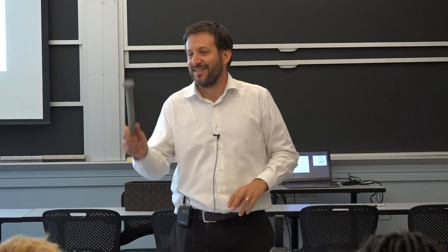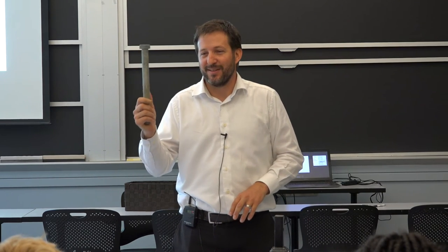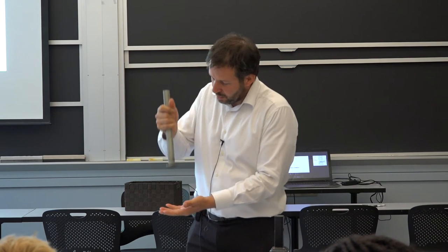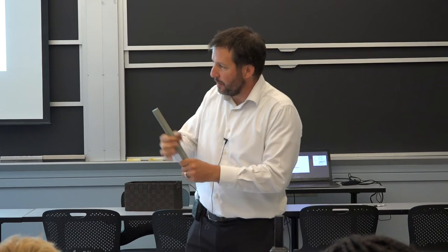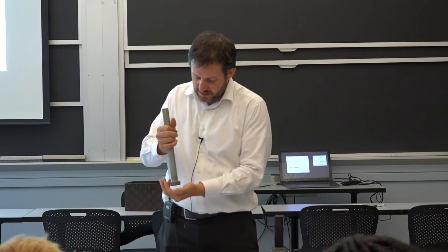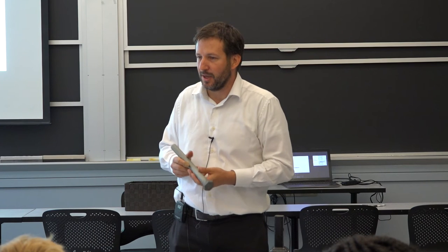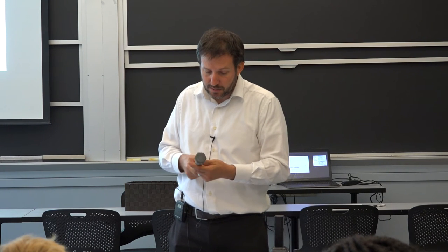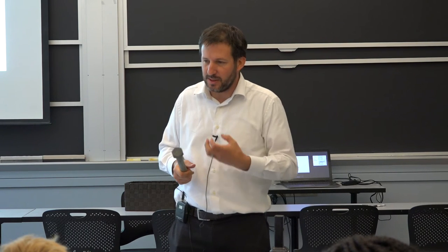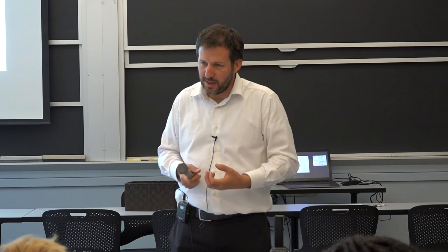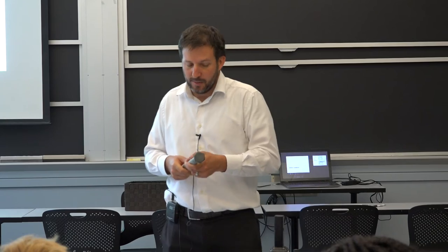What about this one? What do you guys think happened here? Hitting. Yeah, so it's cold pressed. It starts with a bar, and then you have a series of steps to mushroom the end of the bar to make that shape. It's actually very, very strong, so it's not going to break here because you forge the material, you deform it, and you actually make it better than it was to begin with. But you do need to do it by steps, otherwise you'll break it.